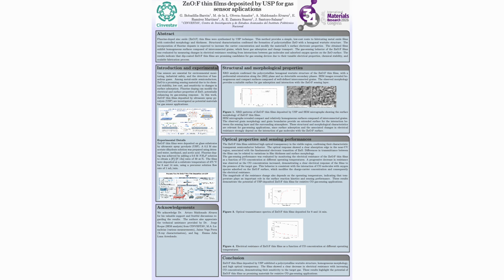Finally, this is probably the most important result of our work. Here we evaluate the electrical resistance of the ZnO:F films as a function of carbon monoxide concentration at different operating temperatures. As you can see, the electrical resistance progressively decreases as the CO concentration increases. This behavior confirms that the films have a clear electrical response to the presence of carbon monoxide. The response also changes with operating temperature, indicating that temperature plays an important role in the interaction between the gas molecules, adsorbed oxygen species, and the ZnO surface.